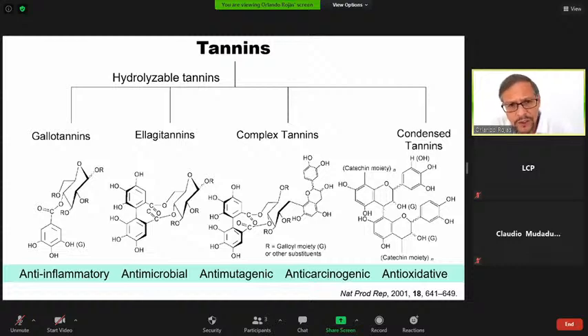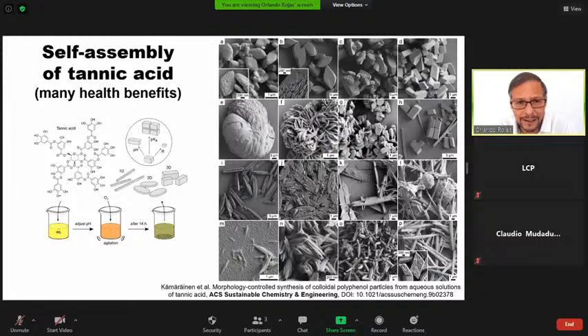And I have always been wondering if we can make such particles of tannic acid in such a way that we can control the shape. Because my hypothesis is that the shape is very important in the applications. We think about cellulose nanofibrils being fibrillar in shape, and in this case we talk about lignin spheres, and here now a variety of shapes for tannic acid particles. So we have been looking into ways to produce tannic particles with a variety of shapes by self-assembly. And this is beautiful because those shapes can be used for targeting different applications. And I believe that different shapes will give different control on the performance of the material.